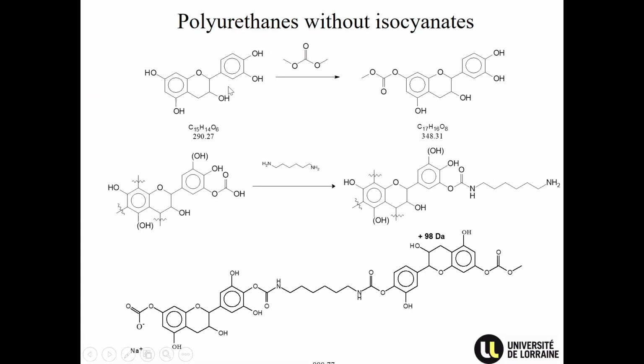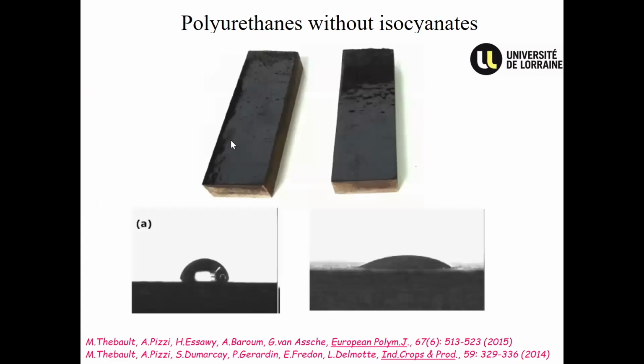So for polyurethane without isocyanate, you can carbonate your tannin, for instance. You react it with the diamine, and you will get your non-isocyanate polyurethane used as adhesive for particle board, and it works very well indeed. You can also see an example as surface finishes. That was the original use of the non-isocyanate polyurethane, called NIPU, and you can see it works quite well as a coating as well.